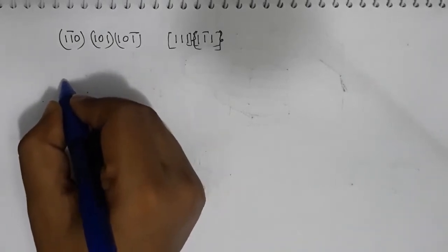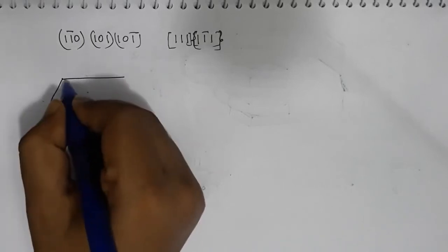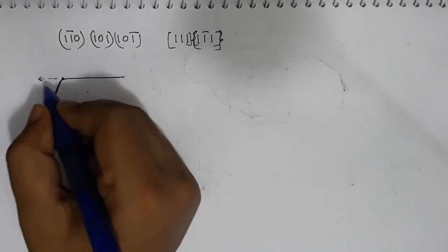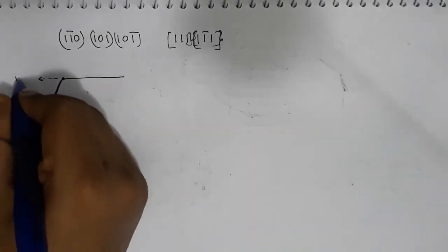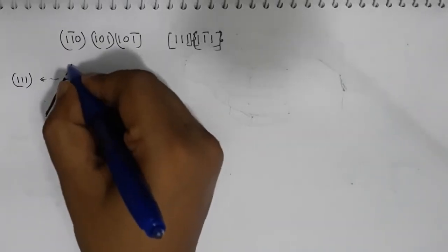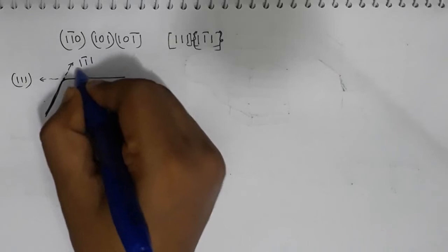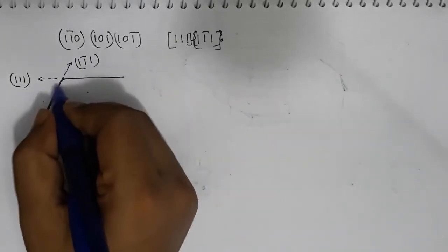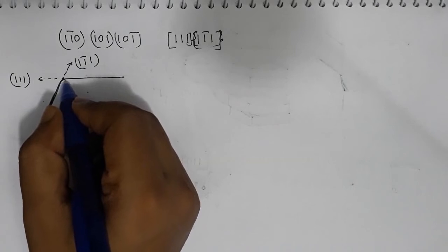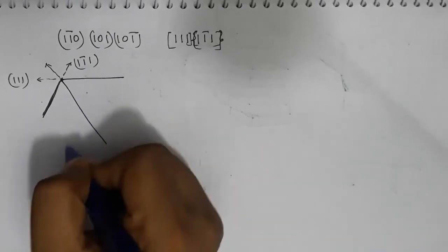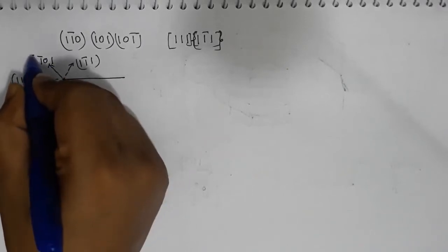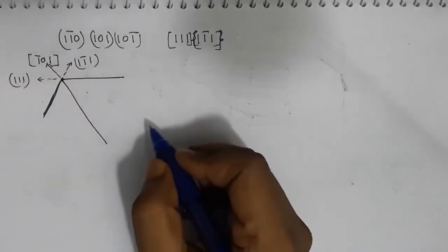Now imagine that there are two 111 planes which are inclined in this way. So this is one type of 111 plane, and this is another plane which is 1 bar 1 1. Okay, and they intersect, and this is the plane of intersection. This is another family of 111 plane, and the direction along which the edge dislocation can move is 1 bar 0 1. So that's the direction where it can move.